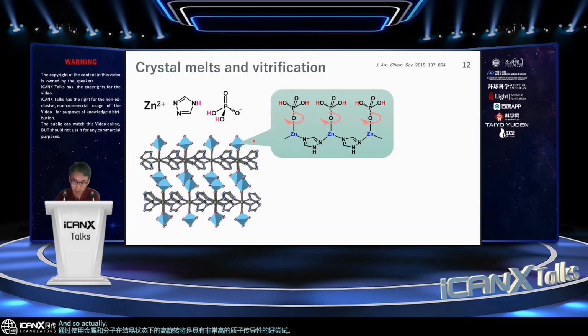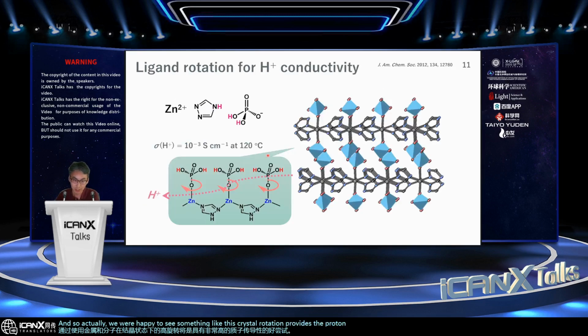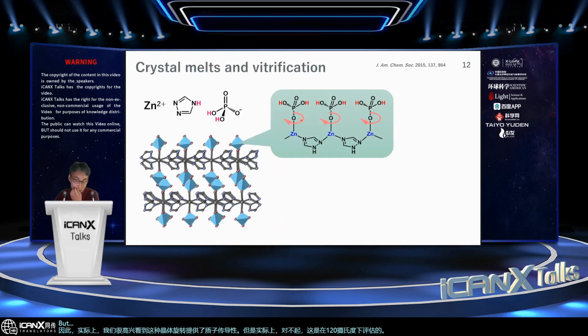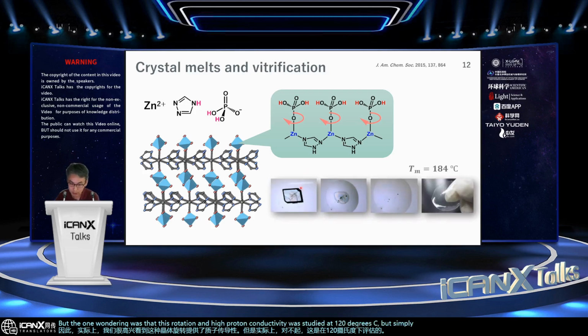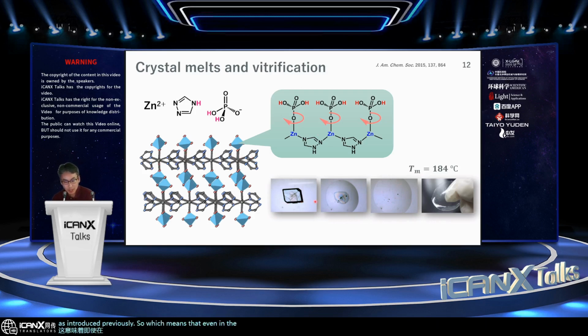We were happy to see that this ligand rotation provides proton conductivity. But this was evaluated at 120 degrees C, okay? One thing we wondered was that the rotation and high proton conductivity were studied at 120 degrees C. But if we heat further, the solid state starts to melt, as introduced previously. Even in crystals, this melting may form because of partial, cooperative rotation inside the structure, which facilitates the melting behavior below 200 degrees C.